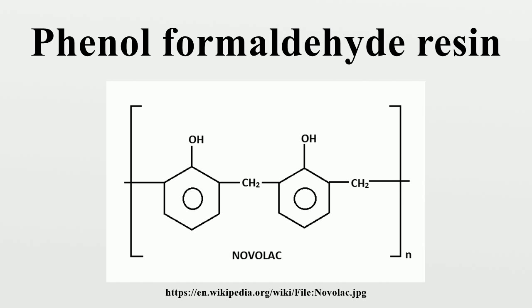Formation and structure: Phenol-formaldehyde resins, as a group, are formed by a step-growth polymerization reaction that can be either acid or base-catalyzed. Since formaldehyde exists predominantly in solution as a dynamic equilibrium of methylene glycol oligomers, the concentration of the reactive form of formaldehyde depends on temperature and pH. Phenol reacts with formaldehyde at the ortho and para sites, allowing up to three units of formaldehyde to attach to the ring.